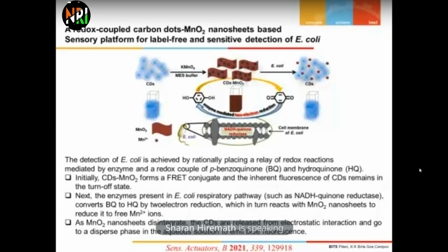Next, due to the enzymatic reaction on the surface of the E. coli, the BQ, the benzoquinone, is converted to hydroquinone by 2 electron reduction, and this hydroquinone further reduces the MnO2 to Mn2+. Now this Mn2+ will settle down and CDs will release into the solution to give out the fluorescence back. This is the simple mechanism which we have adopted for the detection of E. coli.